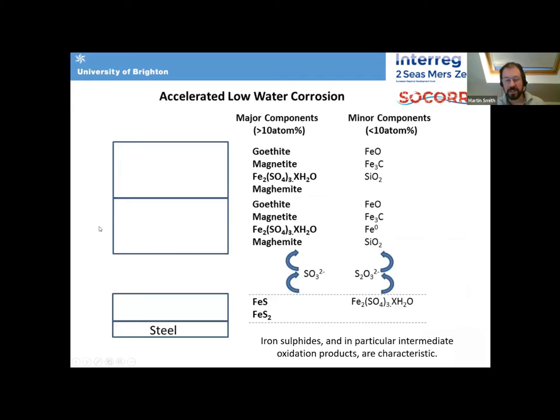But what that has allowed us to do is establish a mineralogical structure to the accelerated low water corrosion. So we go through goethite, magnetite, maghemite, and green rust compounds, the iron sulfates.